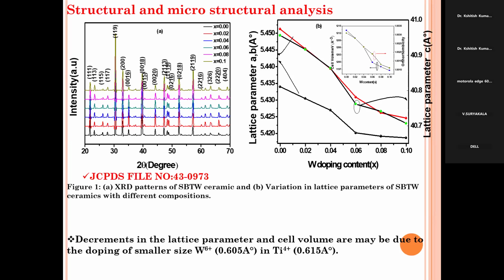Suppose the titanium is 100%, we have taken 2% of the tungsten, then 4, 6, 8, 10, like that. So the tungsten fractions are 0.02, 0.04, 0.06, 0.08, and 0.1. This is the tungsten percentage we have taken. That means we have prepared 6 samples: pure SBT, and the tungsten-doped samples of different concentrations.